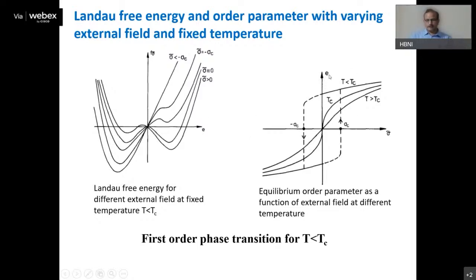This is more clear in this order parameter versus external field plot. This curve corresponds to T greater than Tc, which we discussed earlier. It does not show any phase transition. And this curve corresponds to the isotherm at Tc, showing how the order parameter changes with the external field at Tc. So this shows a continuous phase transition. But as soon as you go below Tc, the order parameter changes discontinuously and it shows a hysteresis.